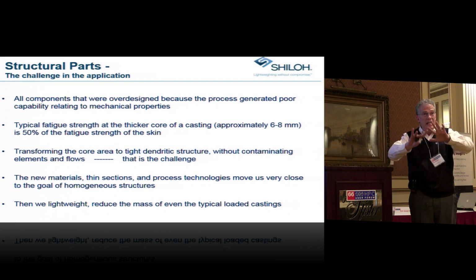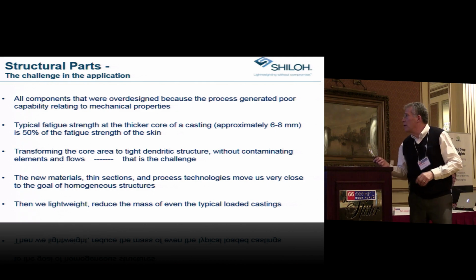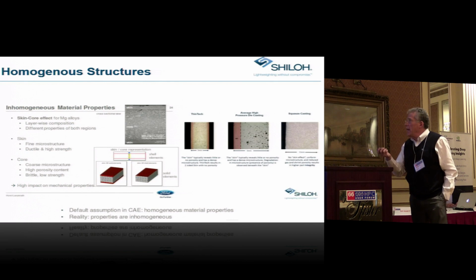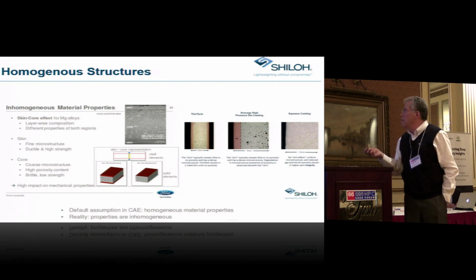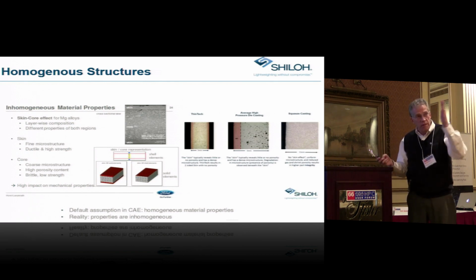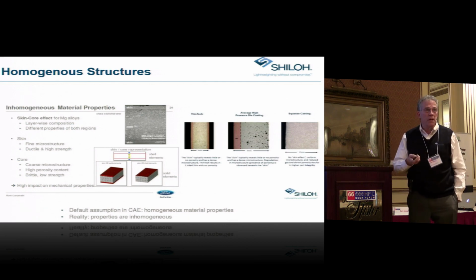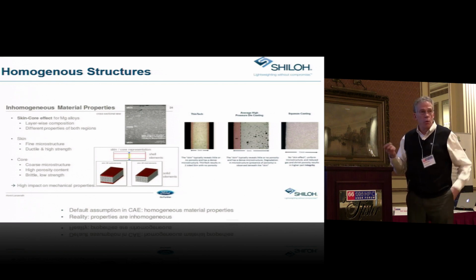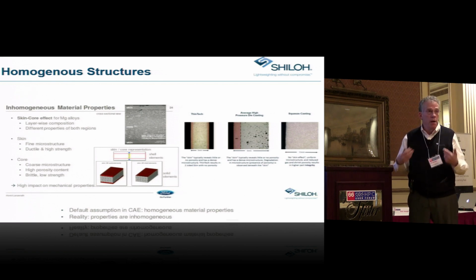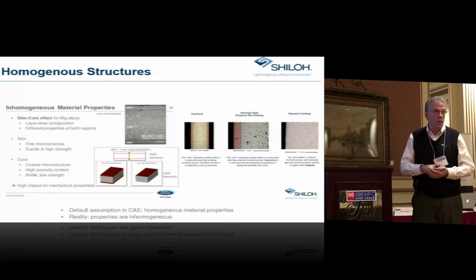You have this fast fill, you have streams of metal that need to flow together, and they need to knit and intermingle, and it's all happening in this 20 or 30 millisecond time window. One of the things you typically have with a typical die casting is a skin which solidifies very quickly, and then a core which is typically full of gas. Now, with metal pressure, Boyle's law will take those bubbles and make them invisible based on the amount of metal pressure you're bringing to bear. But if you try to heat treat the part, they all blow up again